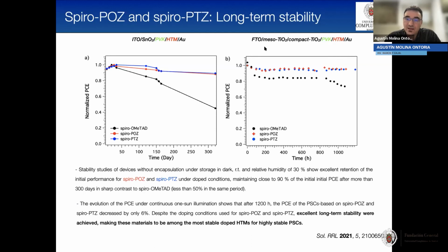On the other hand, we have also measured the long-term stability of our hole transporting material under continuous light illumination in the mesoporous structure, showing only a decrease of 6% after 1200 hours. So this is also remarkable, showing that these devices exhibit excellent long-term stability and making these among the most stable doped hole transporting materials in perovskite solar cells.